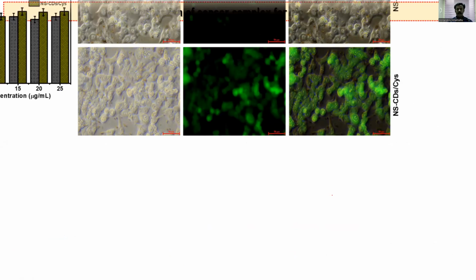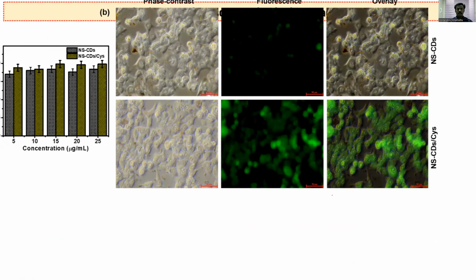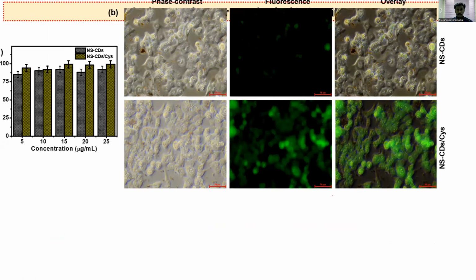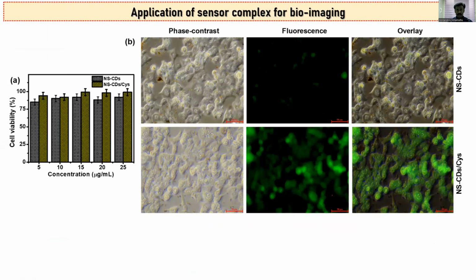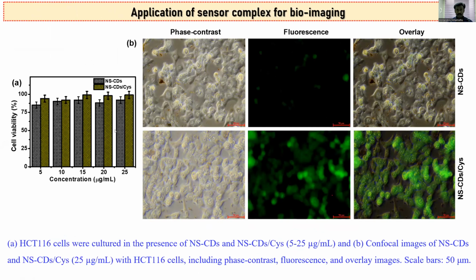The next one is biological applications. The important carbon dot application is imaging. First we have to test cytotoxicity using the MTT assay. It determines the ability of both solutions, the carbon dot and the carbon dot with sensing solution. Different concentrations from 5 to 25 micrograms per milliliter were added to the HCT116 cells. This is a human cervical cell line, and we also measure the stability. After 12 hours, 24 hours and 48 hours we can measure as well.